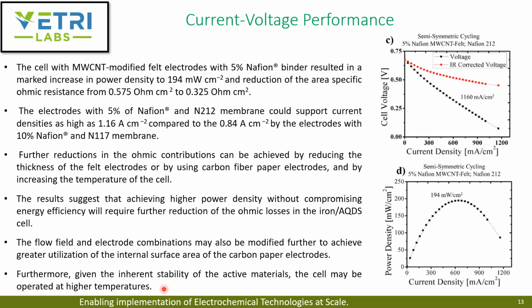And they did the current-voltage performance using the semi-symmetric cycle instead of symmetric cycling, but they changed the Nafion from 10% to 5%, and also used a thinner Nafion membrane. With that, they found that initially they had only 136 milliwatt per centimeter square, and now they have an overall power density of 194 milliwatt per centimeter square. Before, when they used a thicker Nafion membrane at higher concentration, they were able to reach only 840 milliampere per centimeter square. But when they use the lower concentration of Nafion and a thinner membrane, they can reach around 1.16 ampere per centimeter square.